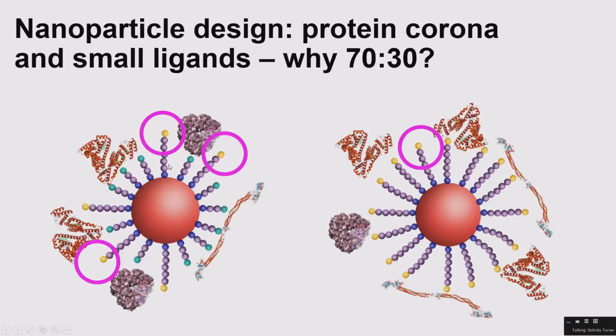Right, so here's just a rough schematic that I've drawn. By using this two-length polymeric system, we have shown as well that the protein corona somewhat forms on some of the shorter polymers, leaving these longer polymers available to bind, versus if we used 100% targeting, there's just one level where the proteins would absorb onto, so potentially having fewer targeting ligands available to bind.